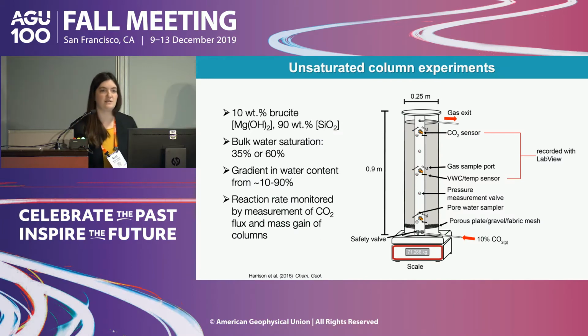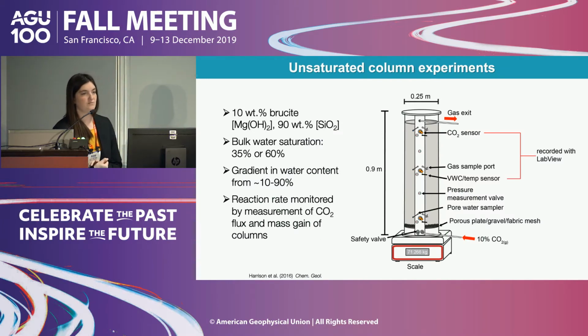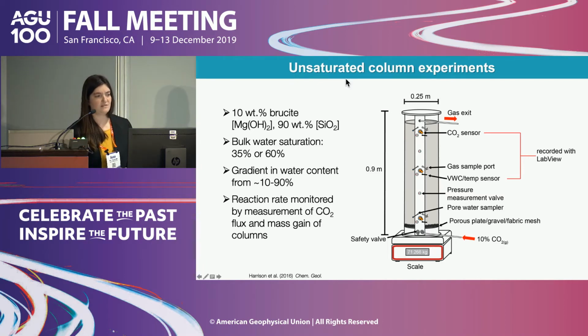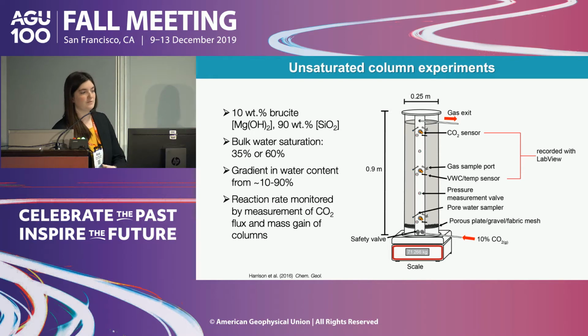One of the ways we can get at this is by looking at results of some column experiments we conducted. These were meter-scale columns that were filled with 10 weight % brucite, which is a magnesium hydroxide phase that reacts readily with CO2 to form carbonate minerals. The rest of the column was 90 weight % quartz, which is effectively unreactive in these systems. It's there more to make up the bulk of the porous medium. We varied the bulk water saturation between experiments, and there's also a gradient with depth, so more water at the base, less water near the top.